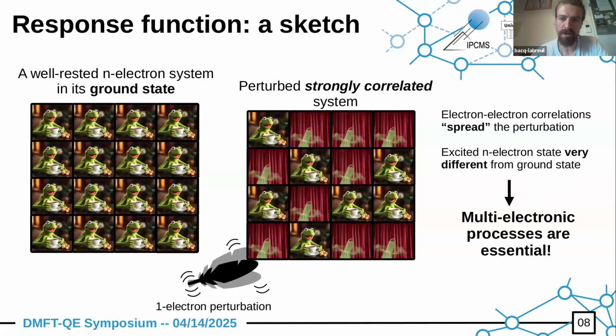However, if your system is strongly correlated, the fact of perturbing one electron, because of the electron-electron correlations, which are quite strong in the material, the correlations would spread all around. And so your excited state, where only one electron is perturbed, is actually very multi-electronic, right? So we need to take these multi-electronic processes into account, because for the physics of cuprates, and I think high temperature superconductors in general, they are actually key and very important. I mean, superconductivity itself is a multi-electronic process.